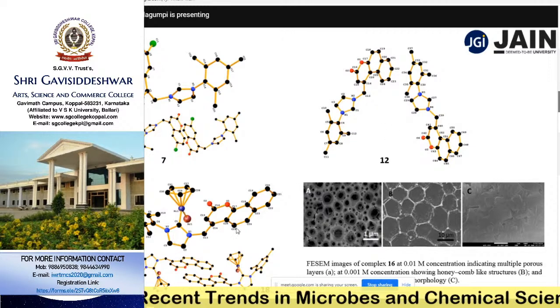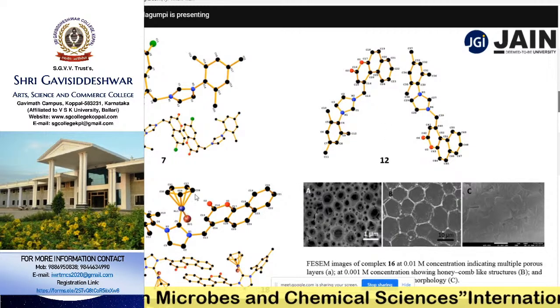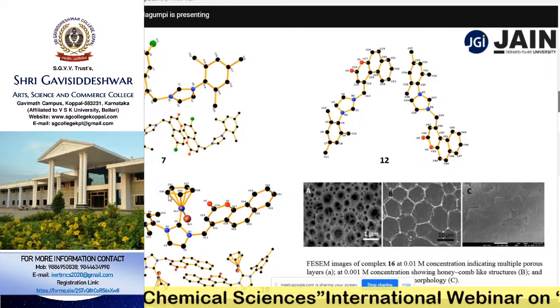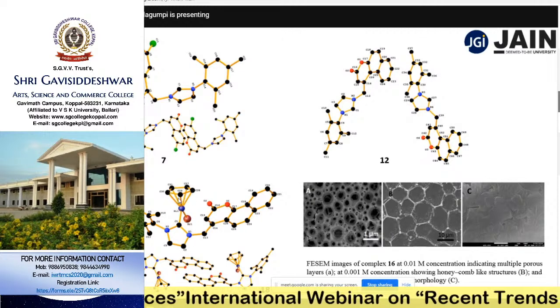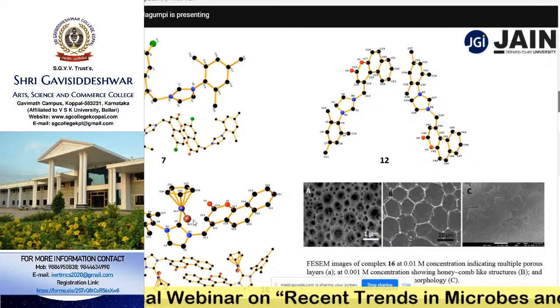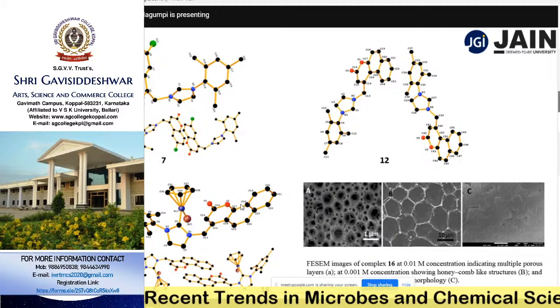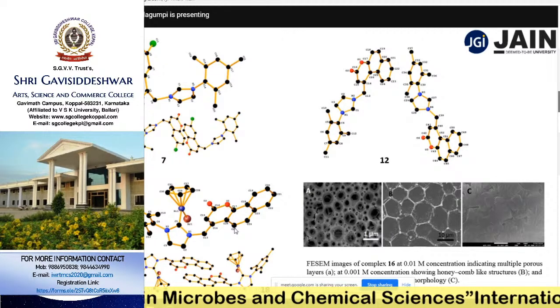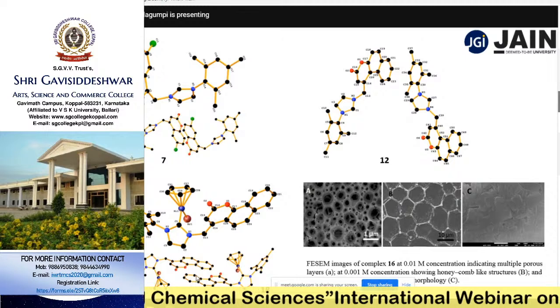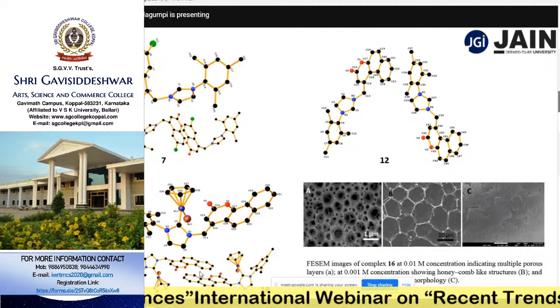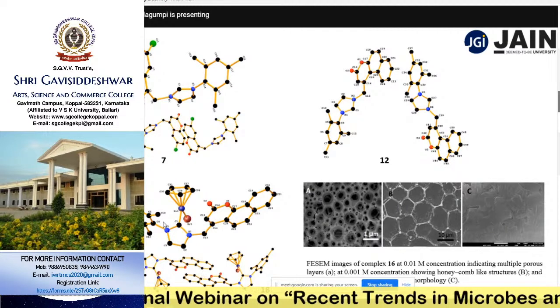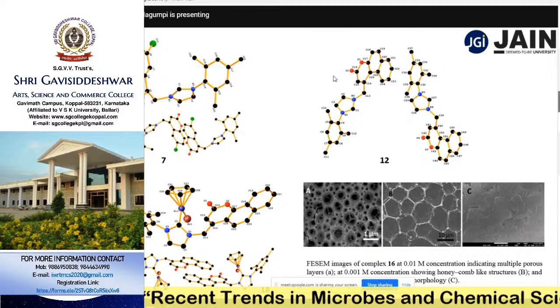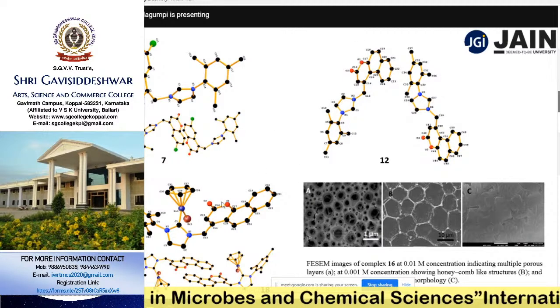Well, this is the X-ray crystallographic structure of the nickel complex. You can clearly see that this is the Cp ring, and all 5 carbon atoms of the Cp ring are connected to the metal center. Along with that, a bromido ligand. So this is the NHC ligand system. And these complexes show pi stacking interactions and extended hydrogen bonding interactions, which stabilize the molecule. So this is about the characterization of the molecule using single crystal XRD.